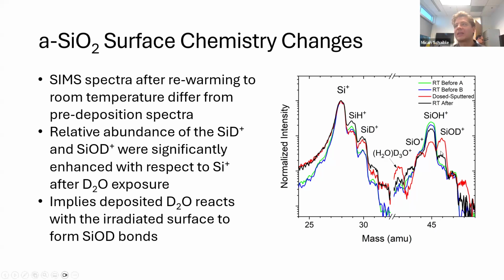But really interestingly, I think, to think about how we can use these secondary ion signals to probe the hydration state of the silicates in the silicate materials. And so depending on the strength of that SiH or that SiD signal, we can get an idea of what is the relative abundance of those deuterated molecules or those hydrated defect species in the regolith samples.